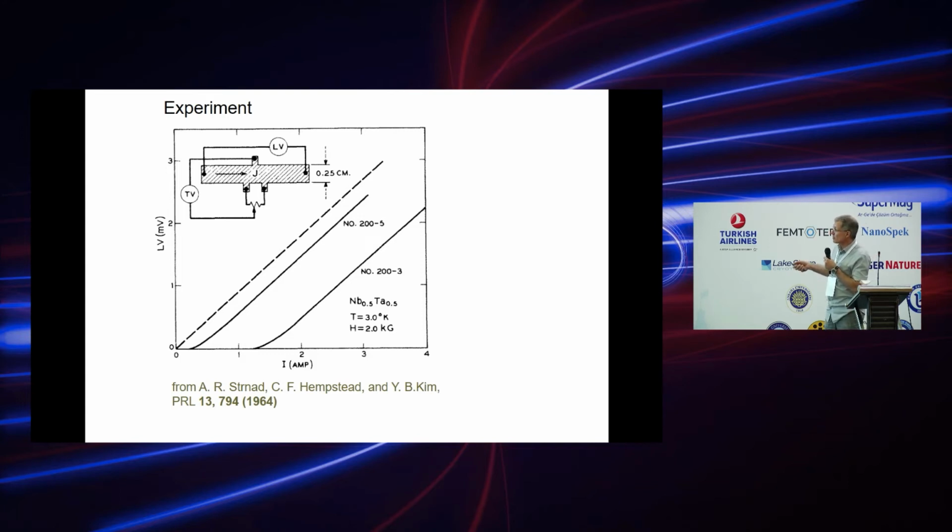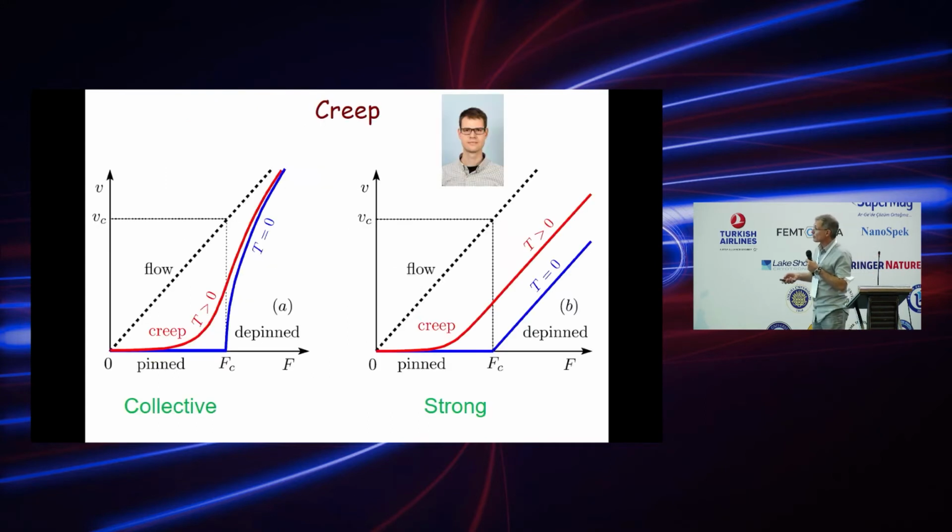And that's flux flow, and that's with the pinning you see it's just the same shifted flux flow, and the essence of the paper was that this slope is proportional to magnetic field, but what we see here is shifted flux flow and a little bit of curvature here that I will come to in a moment.